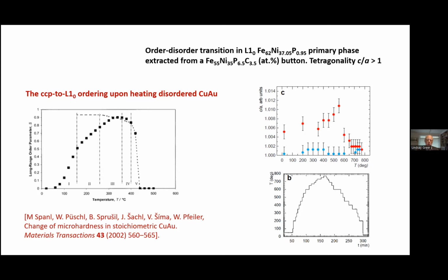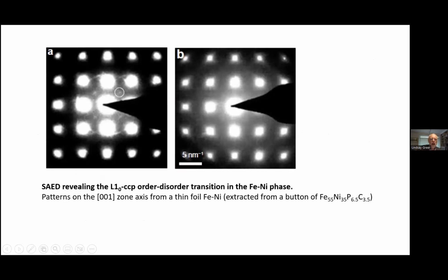When you cool, you would expect the system to reorder, but it does not. We don't really have a good explanation for that, but it is at least of interest that when the same experiment, exactly the same experiment, is done on meteorite samples of tetratenite, just the same thing is seen, that you disorder on heating, but you do not reorder on cooling, and it's probably due to local composition changes.